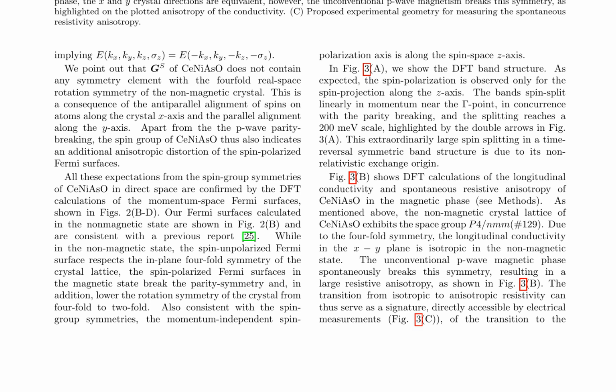The bands spin split linearly in momentum near the gamma point, concordant with the parity breaking, and the splitting reaches a 200 meV scale. This large spin splitting in a time reversal symmetric band structure is attributed to its non-relativistic exchange origin. Figure 3b displays the DFT calculations of the longitudinal conductivity and spontaneous resistive anisotropy of CeNiAsO in the